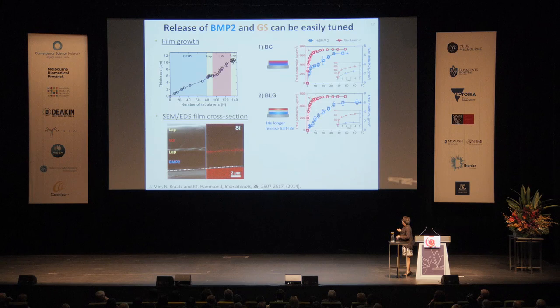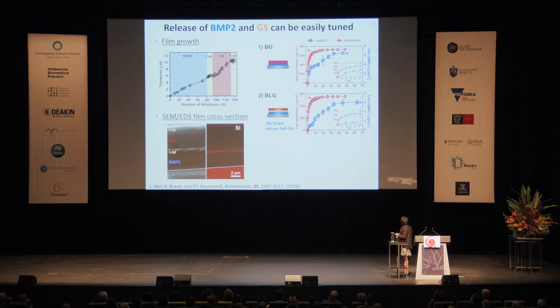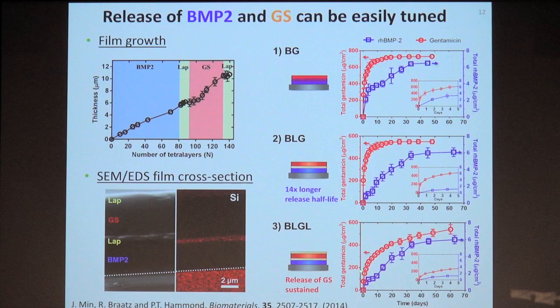She was also interested in this whole idea of not only getting rid of the infection, but preventing any new infection from taking place. Now, you can introduce a bolus, a large amount of anti-infective at once, and that will clear infection, but over time, you might get new bugs that arrive. You need to keep the antibiotic at some sort of critical minimum level to prevent any new bacteria from showing up. So what she did was put a capping layer on top, and that capping layer suppressed the release of the gentamicin just enough that she was able to get a large amount out at once to eliminate infection, and then this sort of extended drain off of gentamicin sulfate allowed us to maintain that minimum inhibitory concentration that we need to prevent reinfection.